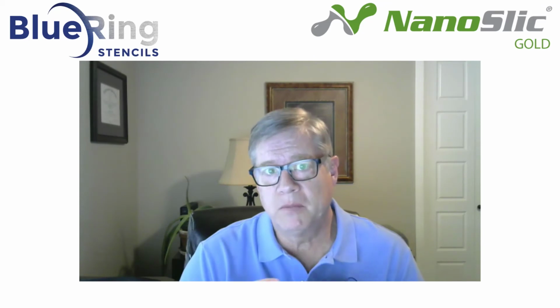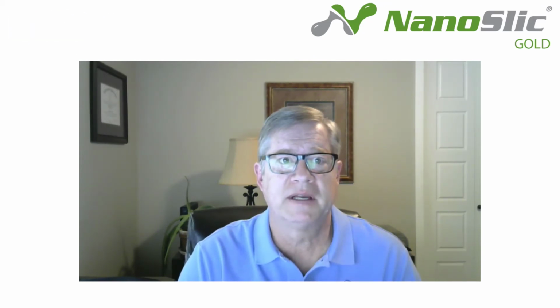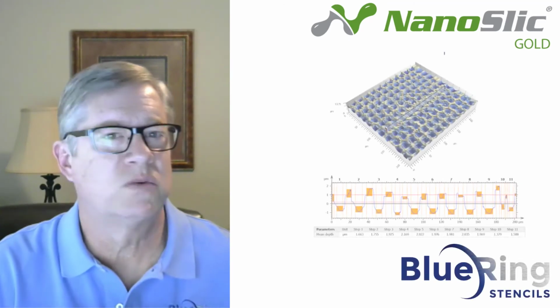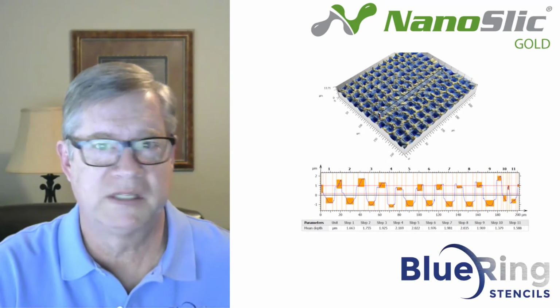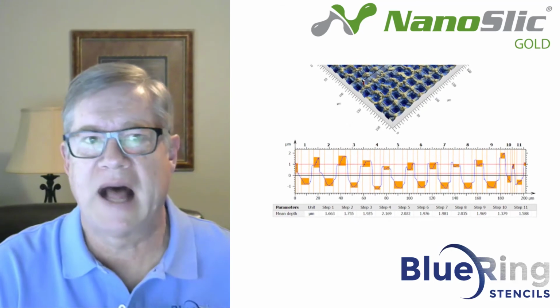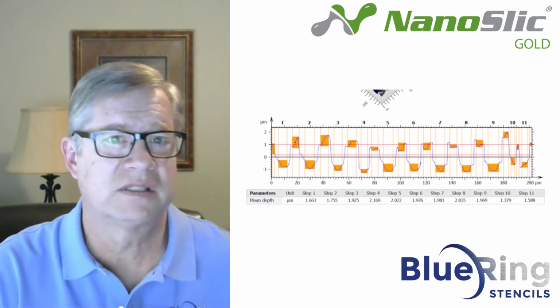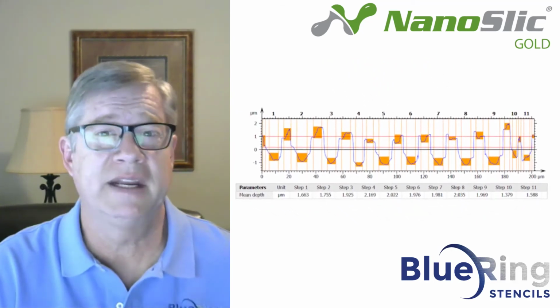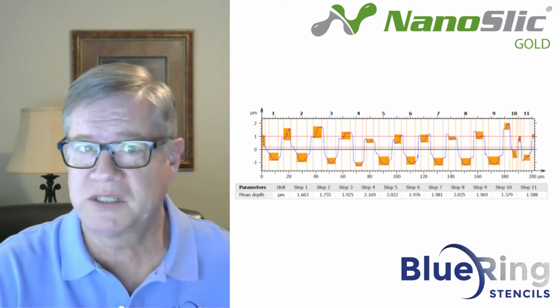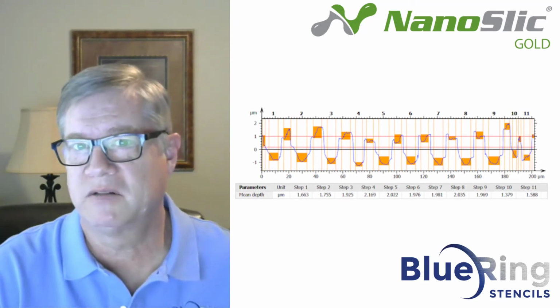Again, you can see we are modifying the surface of the foil prior to coating both physically and chemically. The modified surface is 1 micron lower than the foil surface in some areas and 1 micron higher than the foil surface in others. This surface modification increases the surface area by over 50%, providing better adhesion characteristics.